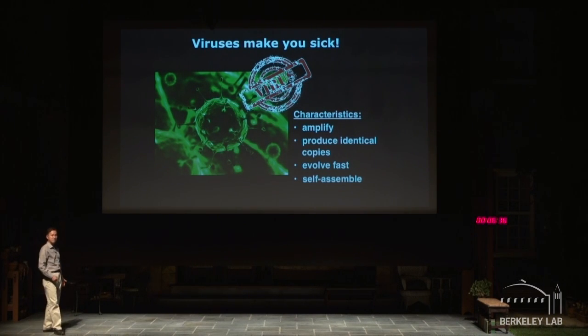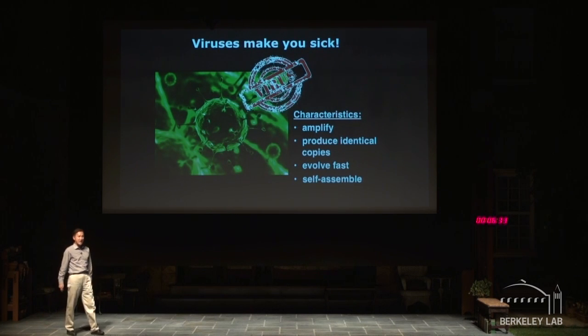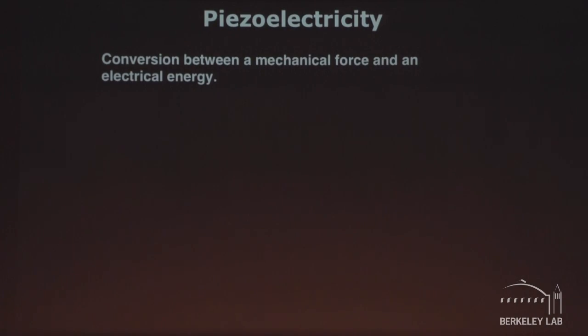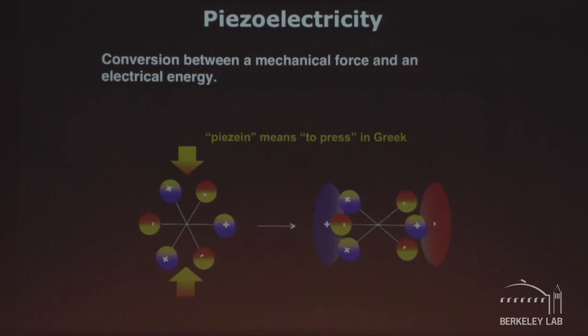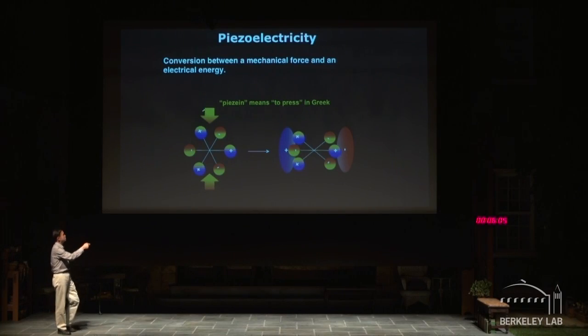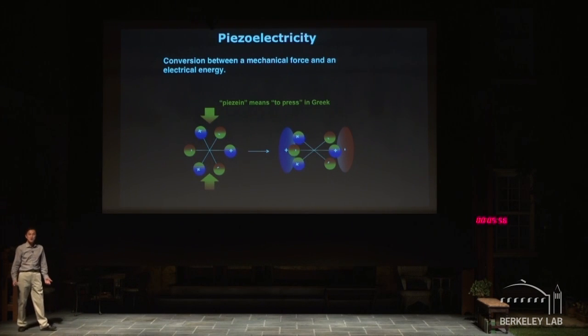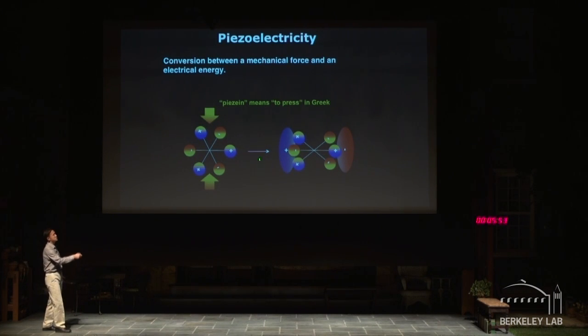Using these characteristics of viruses, we designed new electric energy-generating viruses. The working principle is called piezoelectricity — defined by the conversion between mechanical forces and electric energies. 'Piezo' basically means 'press' in Greek. Piezoelectric materials have charges balanced in a specific ordered structure, and when we apply pressure to these materials, we break the balance of charge and induce partial positive and negative charges, generating an electric potential through the pressure.